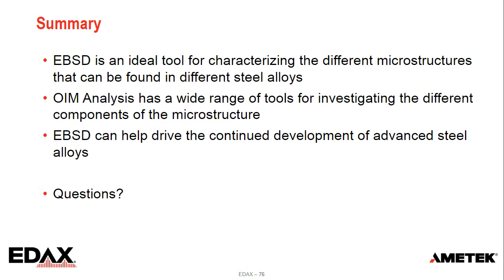And of course, also realize that at 70 degrees tilt, we do have a projection of the interaction volume along one direction of the sample. So your spatial resolution is not necessarily uniform, both along the direction and against the direction of tilt. And so sometimes you have to take that into account as well.